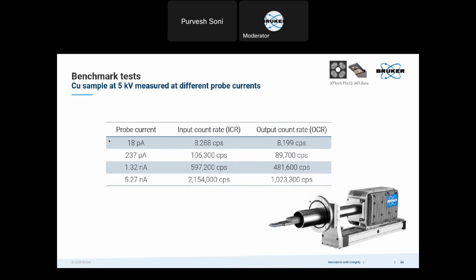At 18 picoamperes, I could get around 8,000 counts per second. And at 237 picoamperes, it was over 100,000 counts per second. At 1.3 nanoamperes, it was 600,000 counts per second. And at 5.2 nanoamperes, it was 2.1 million counts per second. So I can say that if I scale this down, then I can get approximately 4,600 counts per second at 10 picoamperes for copper at 5 kV.